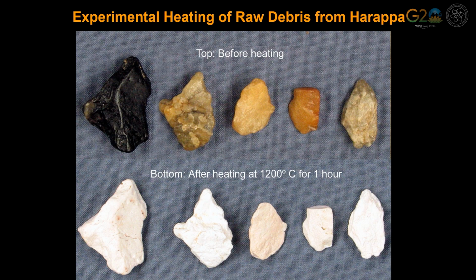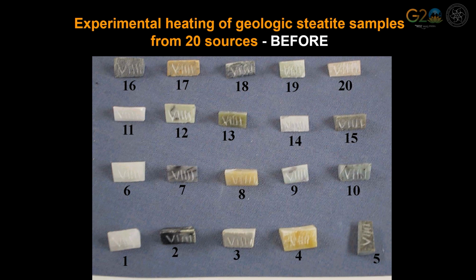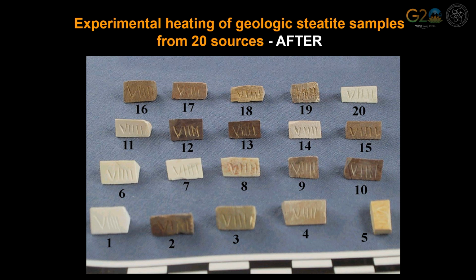One of our initial heating experiments involved different colored examples of the thousands of pieces of production debris found at Harappa. As you can see from this before and after image, the initial raw material color doesn't matter. All become white when heated. This is not surprising, as these examples are of the actual material that Indus peoples brought to Harappa. However, we also conducted this experiment on samples of raw steatite from geologic sources found across India and Pakistan. Here are examples from 20 of those sources before heating. These include material from both dolomitic and ultramafic sources. As you can see from this post-heating image, only a handful of samples became white after being heated. Those that did were exclusively from dolomitic sources.